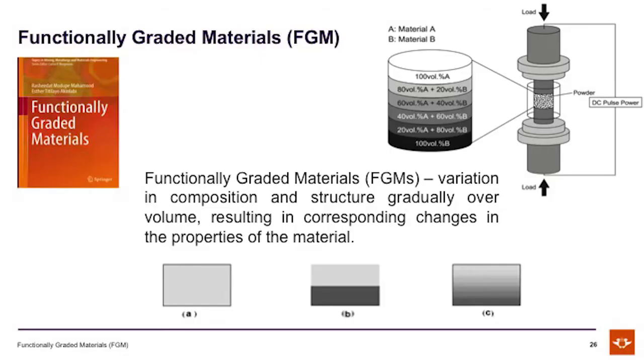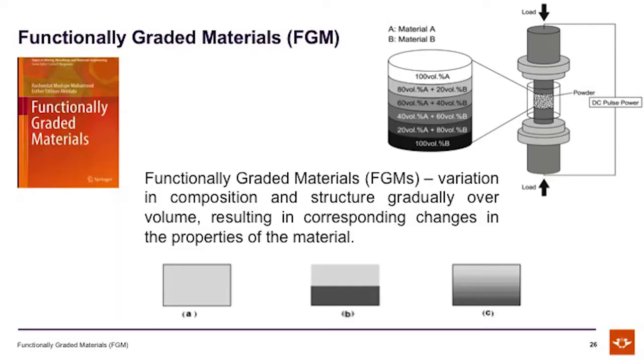Further work on laser-based additive manufacturing is the work that I have conducted in the field of functionally graded materials, popularly referred to as FGM. FGM started in Japan about a decade ago, wherein researchers observed that when laminate composites are used at high operating temperatures, the material tends to delaminate at the joint interface. They needed to come up with a material that is functionally graded in order to eliminate the joint interface. In so doing, they came up with varying the composition and the structure in the material over the volume, similar to what I have in this particular picture.